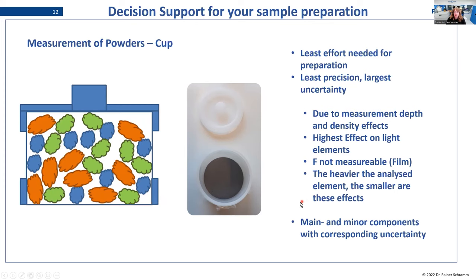The highest effect of all of these effects is on light elements. And the lighter the element, the harsher the effect will be. Fluorine is not measurable in a cup, because we have this thin film parting our powder from our measurement setup. And since we are barely scratching fluorine from the surface of our sample, the film is just in the way. But the heavier the analyzed element, the smaller are these effects.